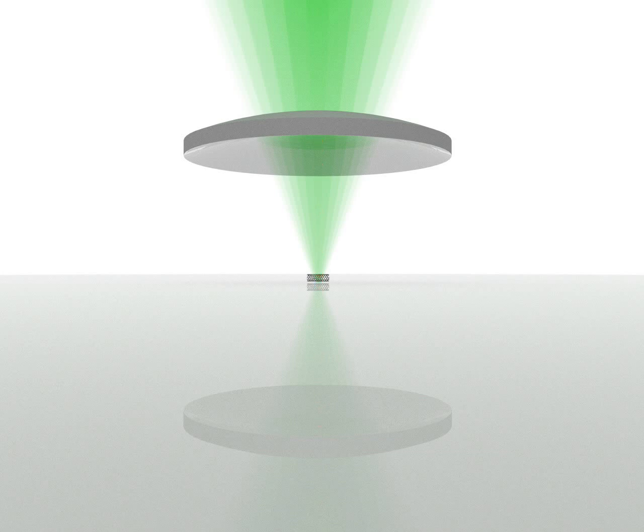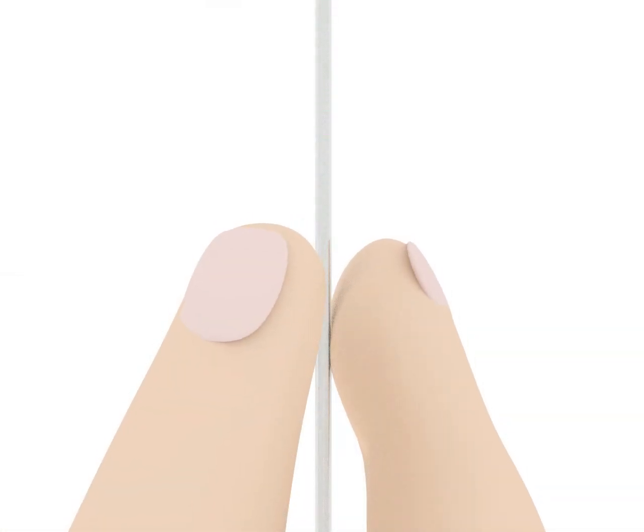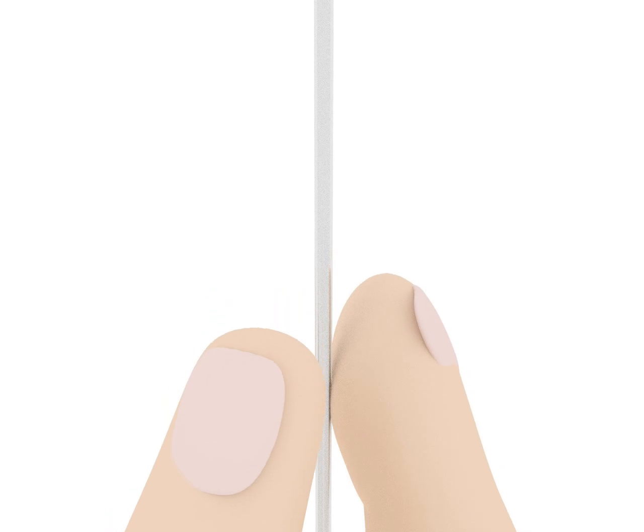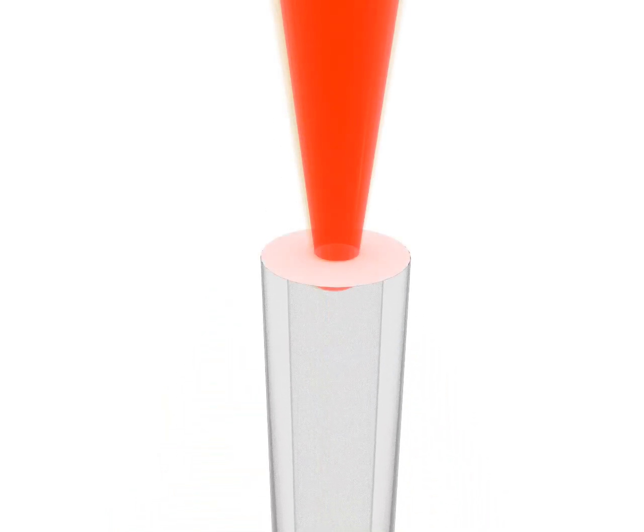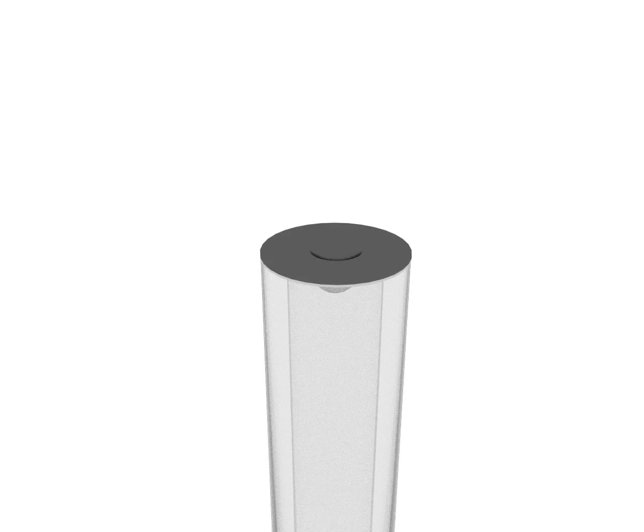It's for doing very small mirrors that we had the idea of using optical fibers. An optical fiber is roughly the size of a hair. With a laser, we shoot the tip of the optical fiber to give it a rounded shape. Then, we put several layers of material to create a mirror that lets past the green light and reflects the red photons.